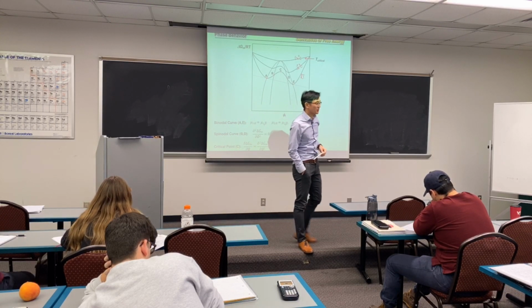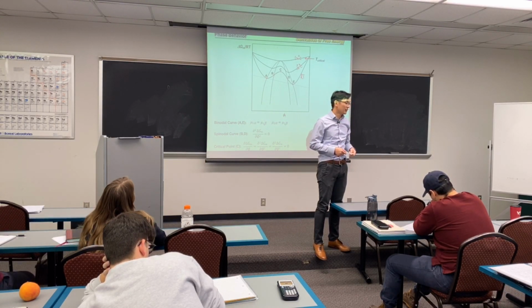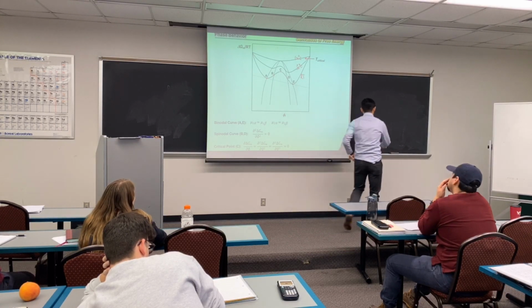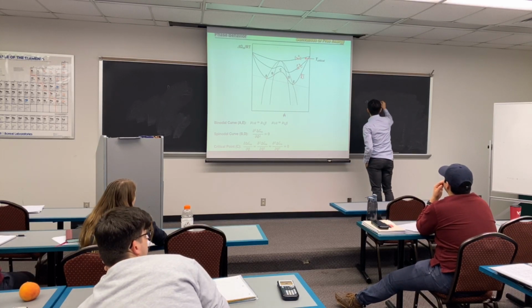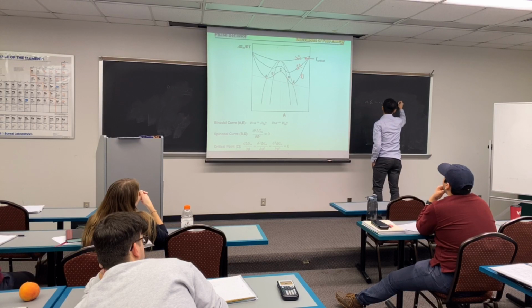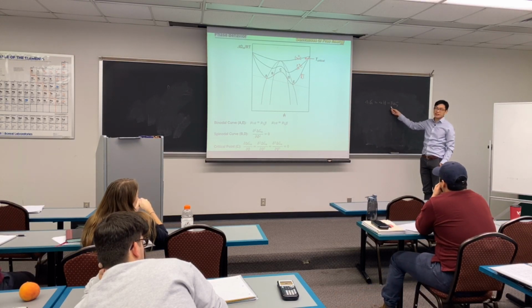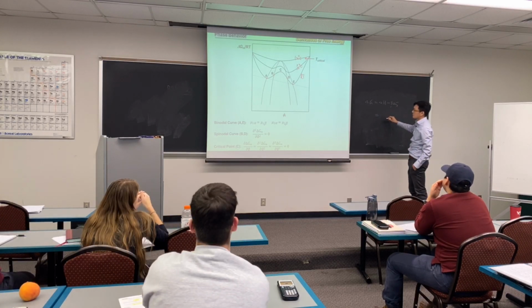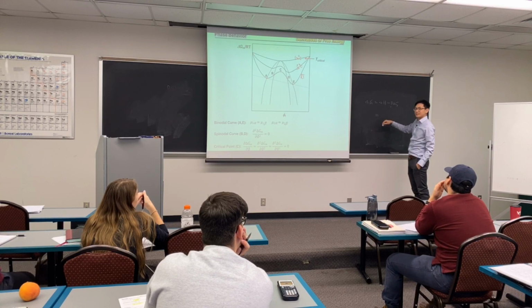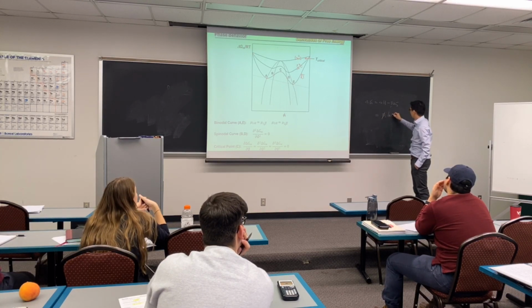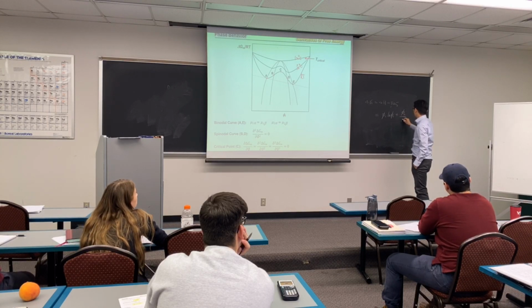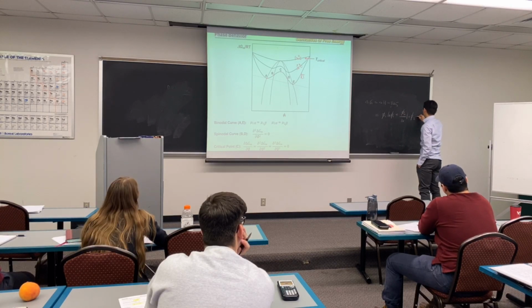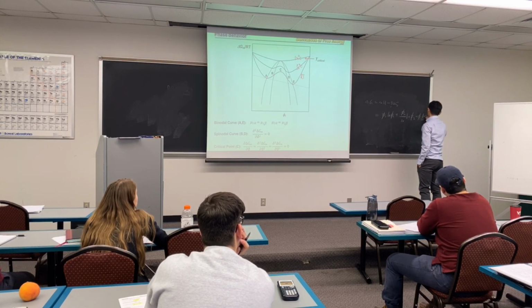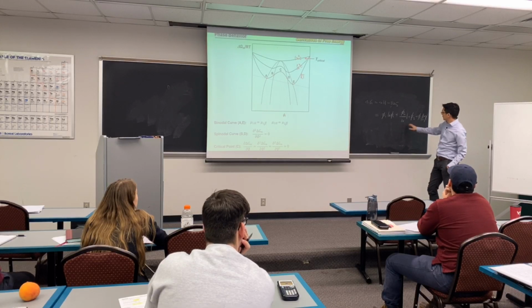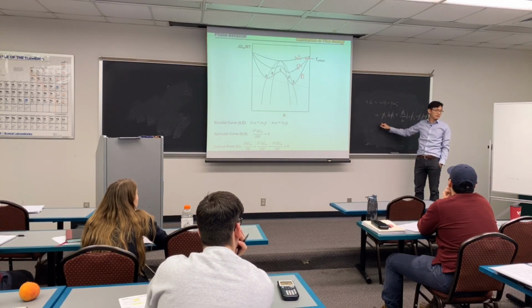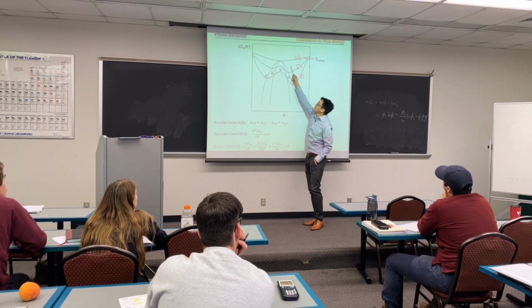That is determined by the entropy and enthalpy terms given by the Flory-Huggins theory, right? So you have delta G equals delta H minus T delta S. And at changing temperature, you would have different values of that. And we can be more specific in the Flory-Huggins theory, let's say for the polymer, that's why your delta G will be a function of phi. And that's how those 1, 2, 3 curves show up.